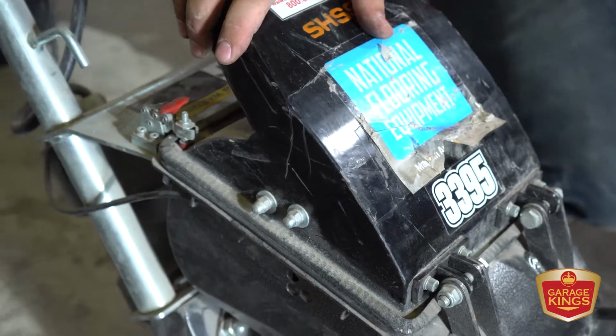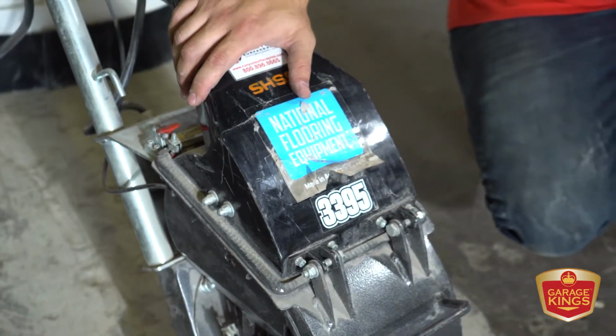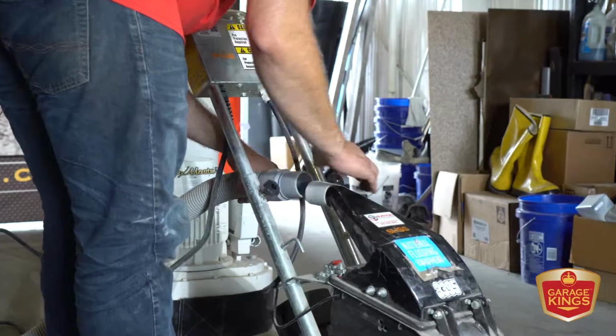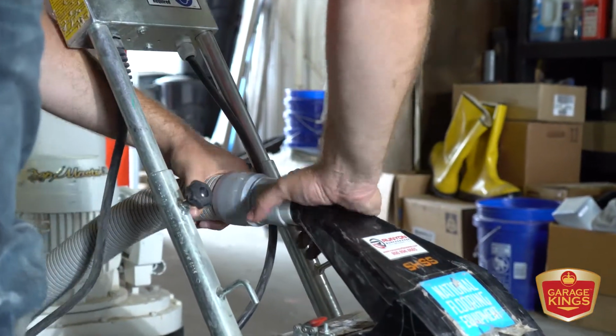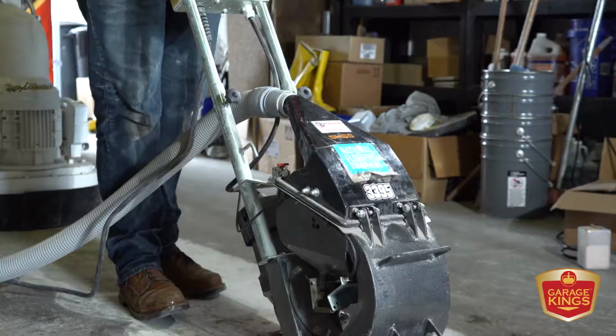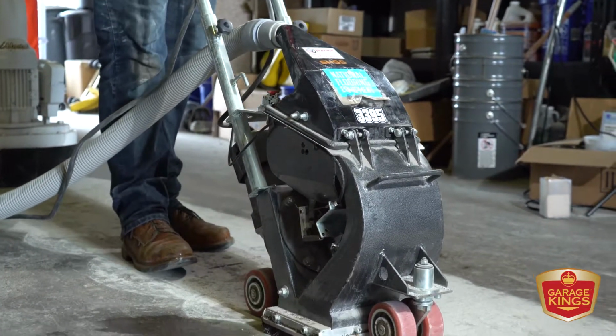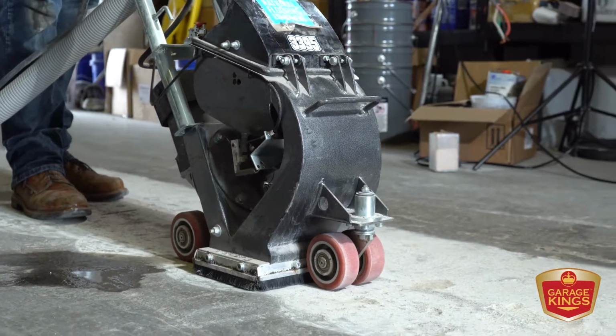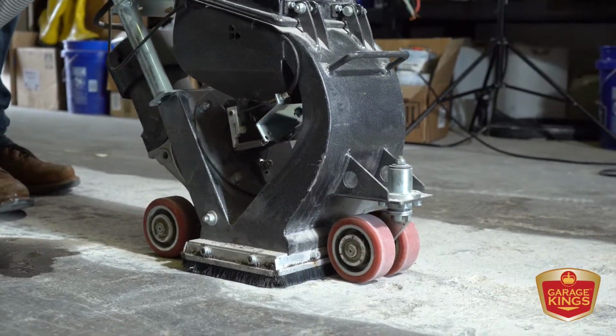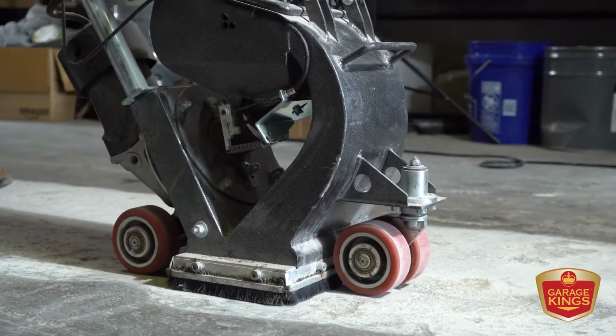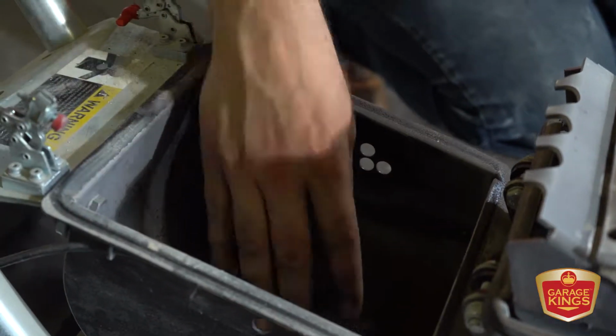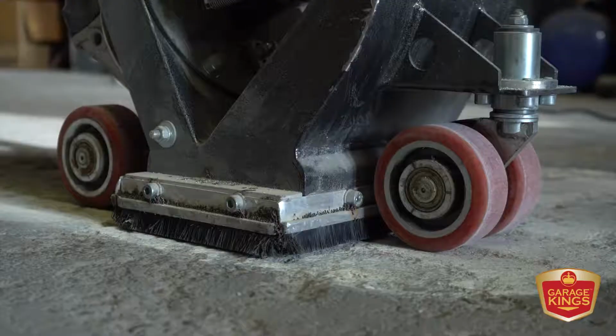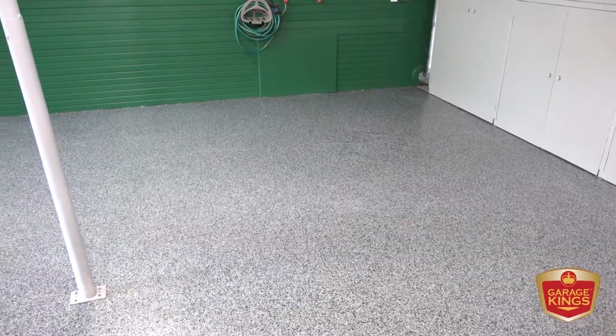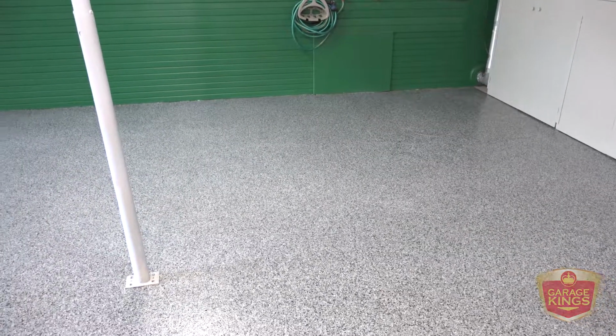This is an additional step. We don't do this on every floor, but ones that are beat up or heavily damaged like this, we will do the diamond grind, and then we'll introduce a shot blaster so that we can go in and prepare all of the low spots. It's important that our material sticks to the low spots as well as the surface. So once the low spots are cleaned out, we go in with a fill material that bonds. We fill in these low spots and we grind everything smooth so that when we install the Signature Flake floor, you don't see any of these imperfections left in the floor. All you will get is a very smooth, clean Garage King Signature Flake floor coating.